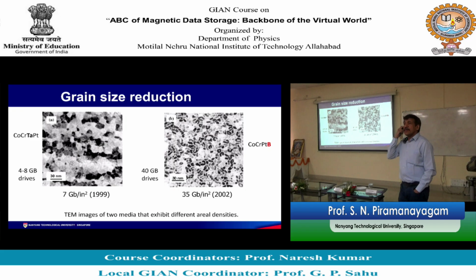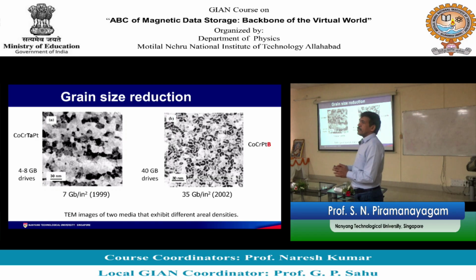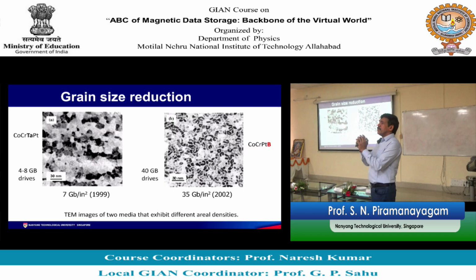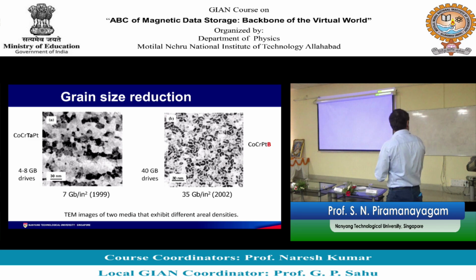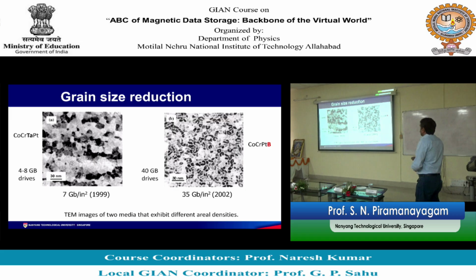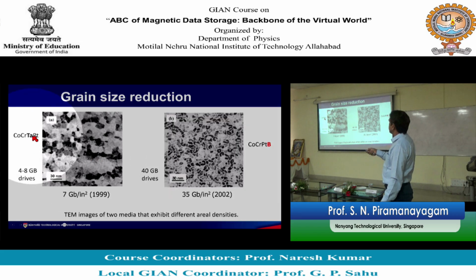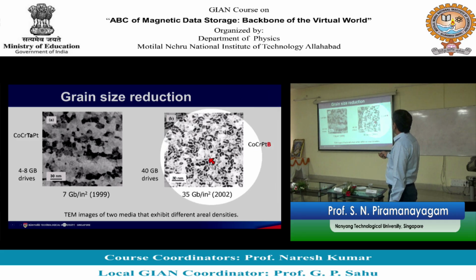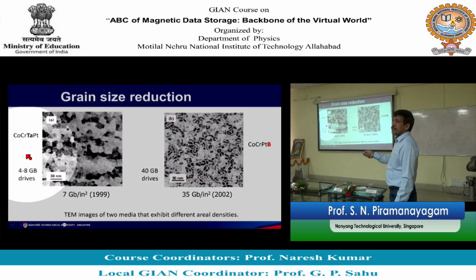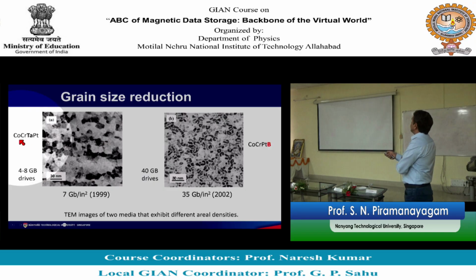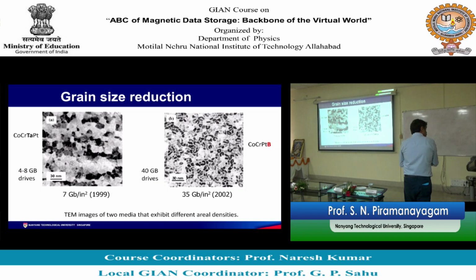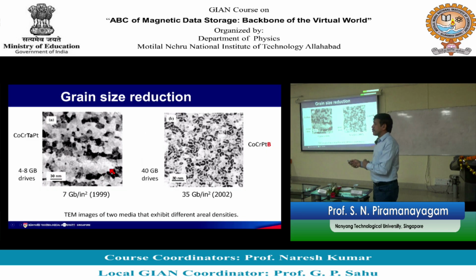So, this again brings us back to the topic we discussed yesterday. Yesterday I told you can achieve compositional segregation. So, you can have grain to be magnetic, grain boundary to be non-magnetic by choosing suitable dopant and suitable deposition condition. In this case the dopant material was tantalum, but in this case the dopant material was boron. So, when you use boron, the boron and some other elements diffused the grain boundary very well, much better than what we discussed yesterday. So, by choosing suitable dopant material, they could make the grain sizes smaller. So, this is one way to progress.